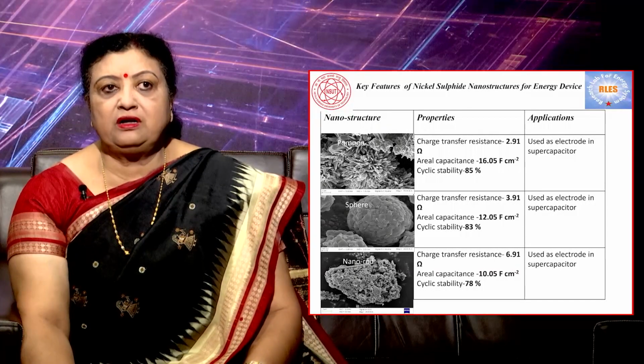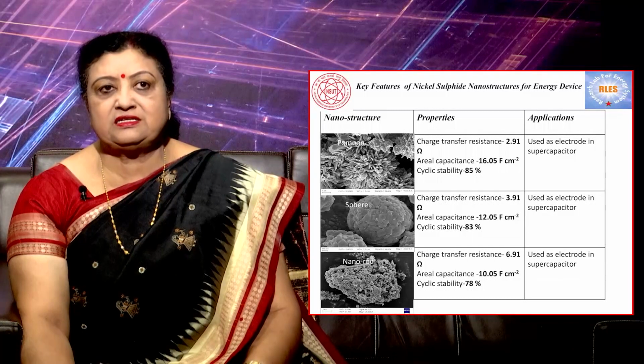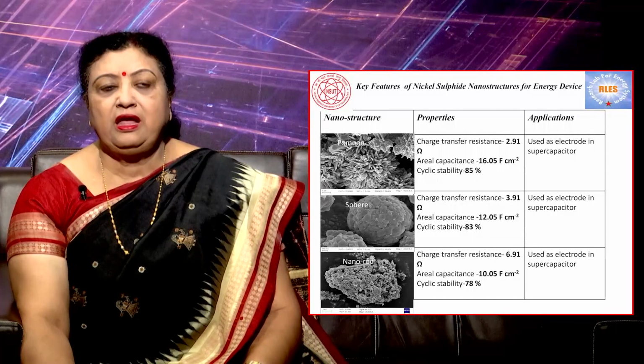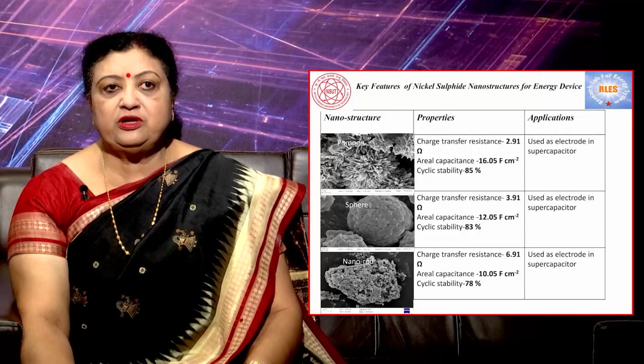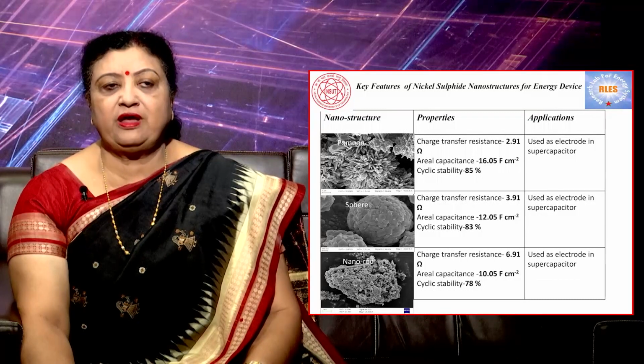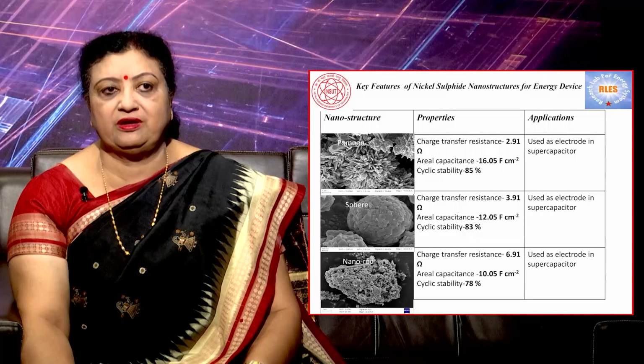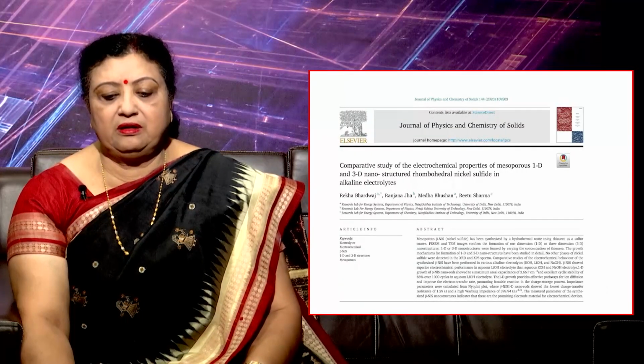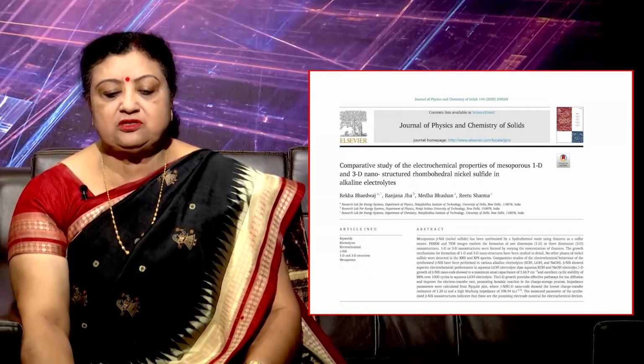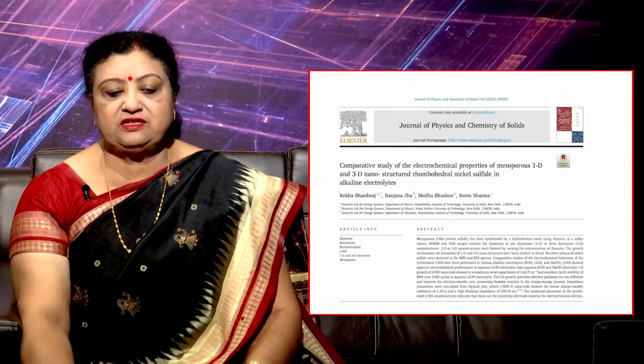The nanorod: charge transfer resistance 6.91 ohm, areal capacitance 10.05 farad per centimeter square, and the cyclic stability is 78%, and it can be used as an electrode in the supercapacitor. The paper which we have published on these types of nanostructures.